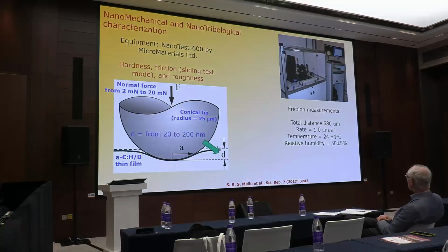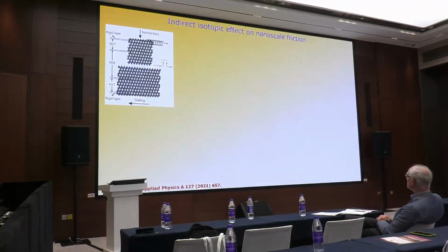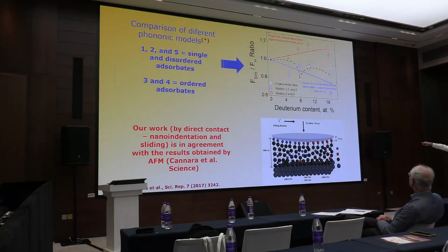Let's go back to our results. Okay, here. The squares are the experimental data, and the others are the models, for which we used some parameters and put the results. Models 3 and 4 are models of ordered adsorbate. When you have an ordered adsorbate position, you have an organized surface. And models 1, 2, and 5 are for single and disordered adsorbate.